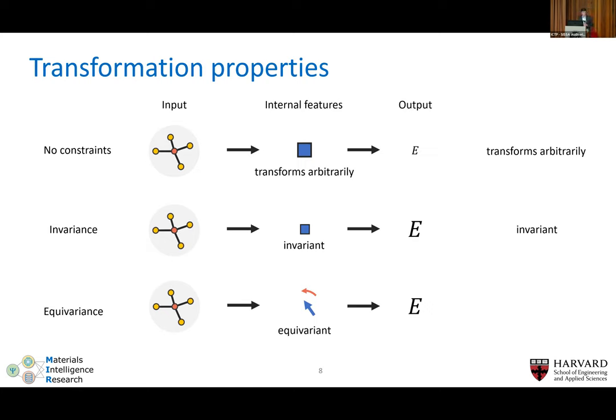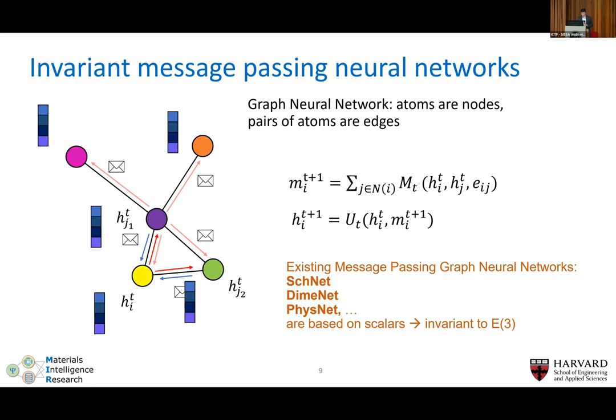To build a neural network model of interatomic potentials, the typical approach today is a graph neural network with message passing. Atoms talk to each other and send messages through graph convolutions, encoding what each atom sees around it — distances, angles, invariant properties. These invariant messages are passed to other atoms, and through multiple layers the network encodes a lot of information, achieving quite good accuracy when learning the energy.